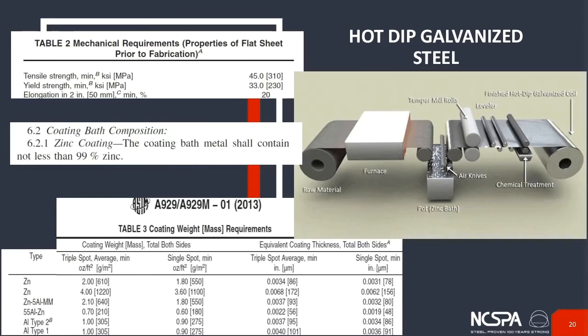So specifications for the steel itself, you can see at the top there on the left, yield strength, a minimum of 33 KSI. We're pretty particular about the properties for what we call culvert coil, because we're going to turn this material, we're going to corrugate it, bend it. So it's got to be a pretty specific spec material for our use. In the middle, again, you can see the coating bath is 99% zinc. And at the bottom graph, that's from ASTM A929, and the top line is zinc. And again, it's a 2-ounce coating. You can measure that in terms of weight and what the thickness is using very specific test methods.